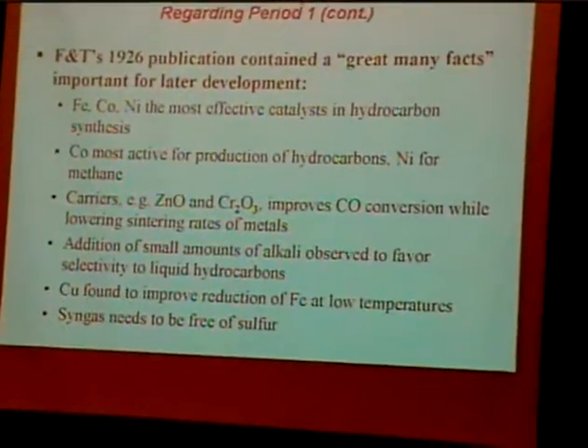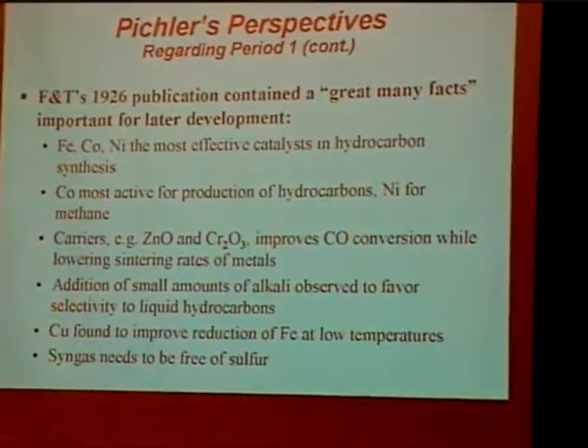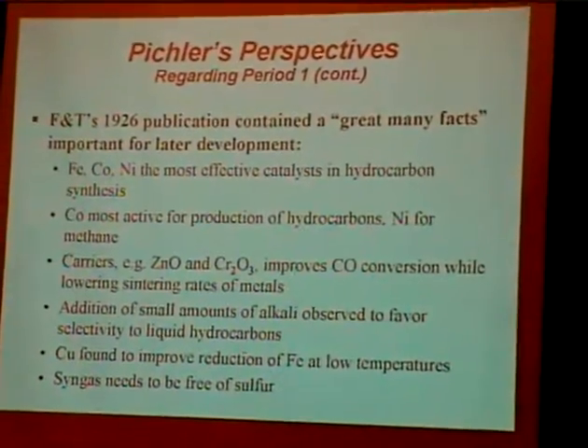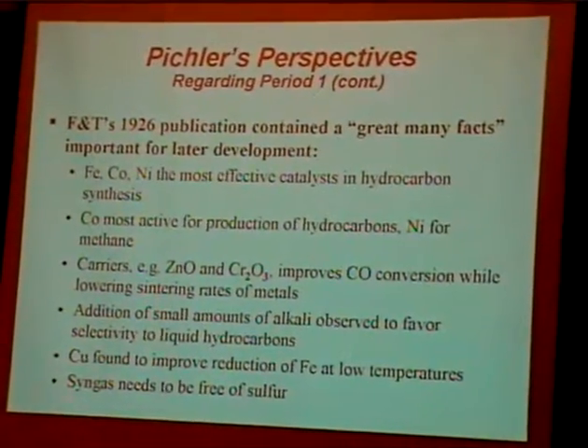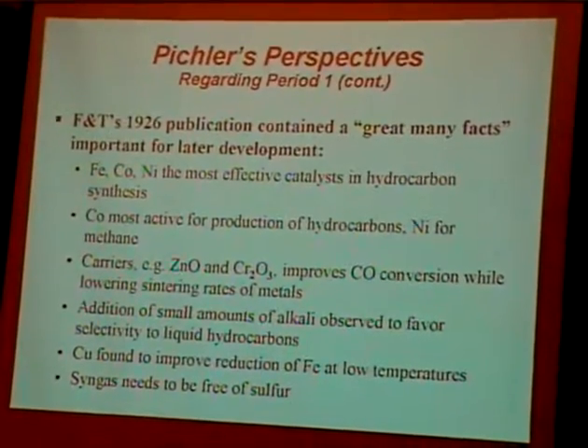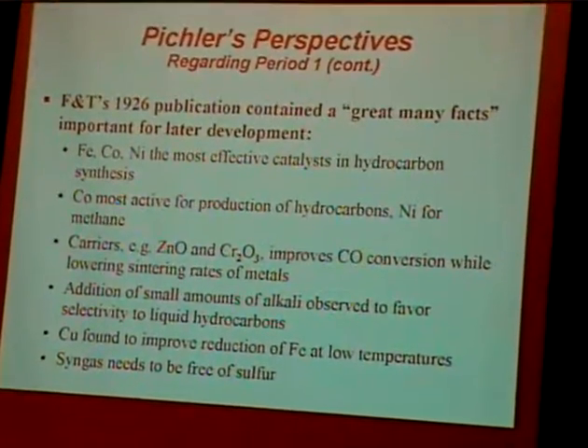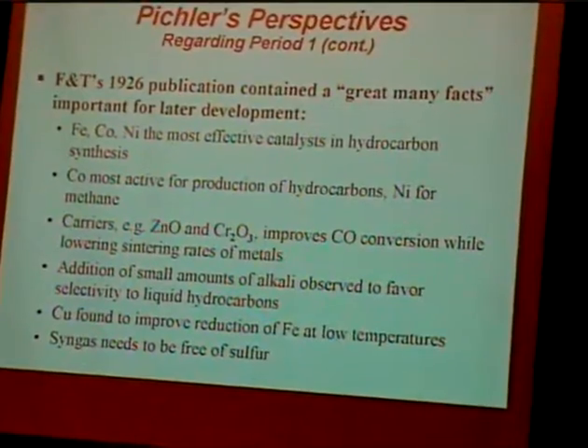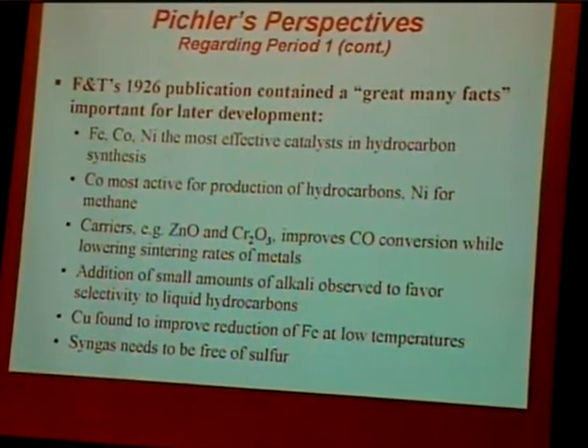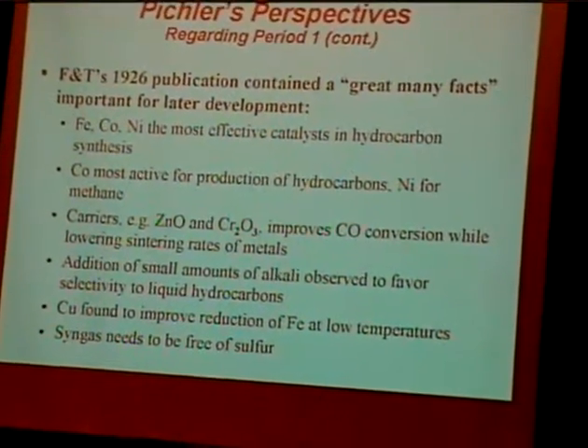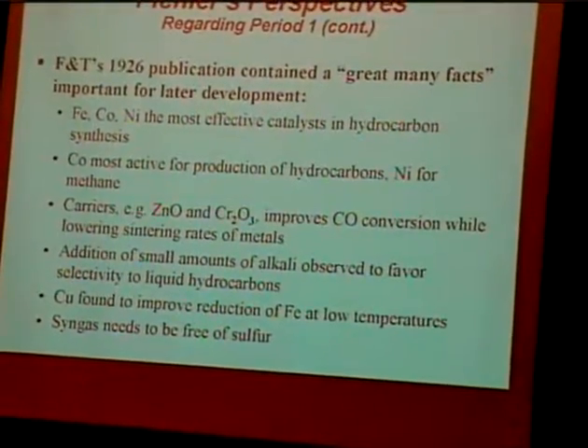Carriers such as zinc oxide and chromium improve CO conversion and prevent sintering of the metals. Addition of small amounts of alkali were observed to favor selectivity to liquid hydrocarbons. Copper improved reduction of iron, and syngas needs to be free of sulfur.